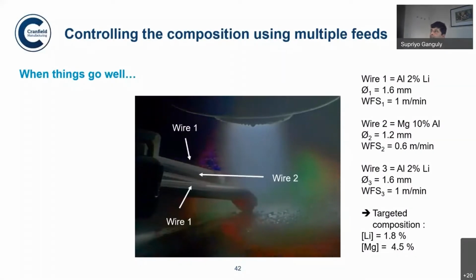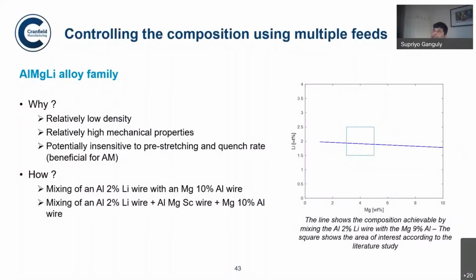So you can see here that we are trying to mix aluminium lithium with aluminium magnesium, and the target composition is shown here: we wanted about 1.8% lithium and 4.5% magnesium. This is being tried because we found that the aluminium magnesium lithium alloy family can give you relatively low density, and the lithium increases the specific modulus quite significantly, which is Young's modulus divided by the density, and is quite high when we have lithium in the mix, and it is potentially insensitive to pre-stretching and quenching rate, which is enormously beneficial for AM.